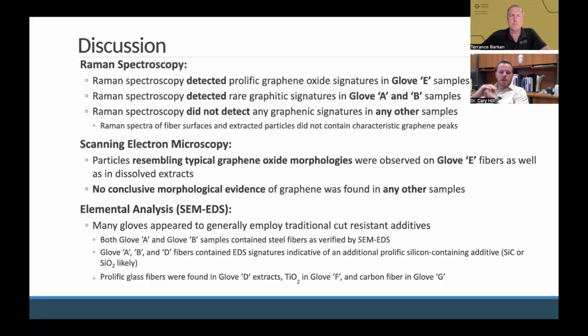And also we found concurrently, that's why we like to use multiple techniques, to make sure we have concurrence between our techniques and not just relying on interpretation of one instrument. We did find that we have these thick flakes that were graphitic. And there are other techniques we use, which we talk about in the paper, in situ with the electron beam. Basically, by jacking up the electron beam, if it's polymeric, it'll burn. If it's graphite, it's resilient. And so there are other, more subtle methods that we use to verify that this is graphite content and it's carbonaceous. So we did find some material there.